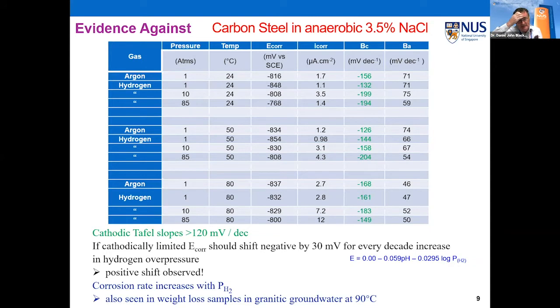But if we go back to our thermodynamics, which is where I always like to start, if it was cathodically limited, we should see a shift of 30 millivolts for every decade increase of hydrogen pressure, again from our Nernst equation. But actually what we see in the open circuit potential, if we look at E-corr, is that it's shifting positive. So it's going the wrong way. And also as we go to higher pressures, except for this one, in the majority of cases we get higher corrosion rates. That doesn't fit with the idea that the bacteria remove the hydrogen and make the corrosion rate go faster. I also found from weight loss in granitic groundwaters, admittedly at 90 degrees, that higher hydrogen actually resulted in higher corrosion rates, not lower corrosion rates.